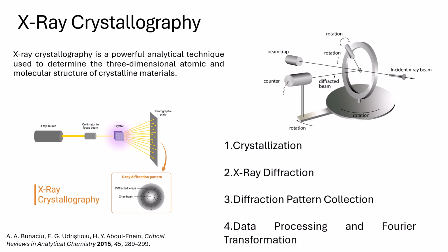So shown here in the plot is a very basic and abstract setup for the X-ray diffraction. We have a holder that can hold the high-quality single crystal needed for the X-ray diffraction, and we have beams that project through this single crystal sample. It can be rotated so that the diffraction pattern can be collected. And after we get all the diffraction patterns, we will do the data processing and refinement to build up the electron density map and help us find out the actual atomic structures right there.